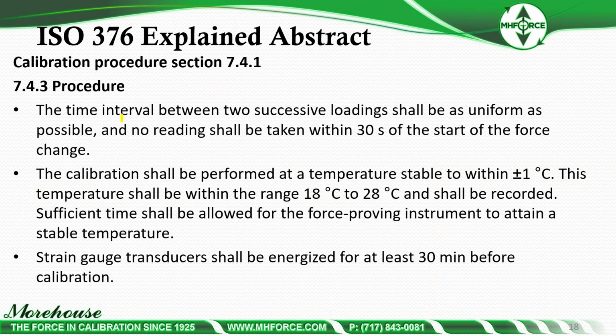So again, time interval. If we look at the time interval between two successive loadings, ISO says it shall be as uniform as possible, and no reading shall be taken within 30 seconds of the start of the force. This is interesting because lots of people using transfer standards or using the automated machines with servo controls and hydraulics, the machine just ramps right up, takes readings, and ramps right down.